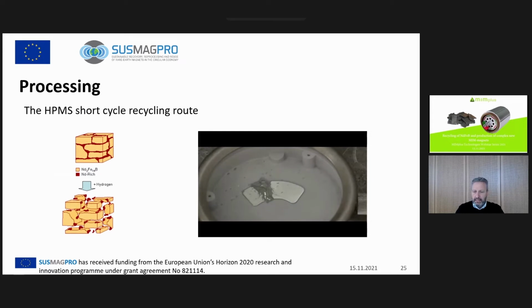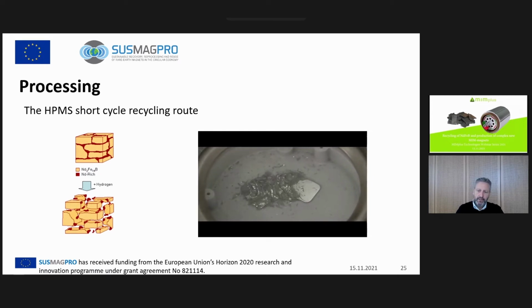Then the recycling itself is a fantastically simple process because neodymium iron boron is very reactive to hydrogen. So what happens if we introduce hydrogen into the magnetic structure? You have the hard magnetic phase, which is the light orange part. This remains fairly unaffected by the hydrogen, whereas this grain boundary phase takes in the hydrogen, forms the hydride, and this hydride is bigger in volume.